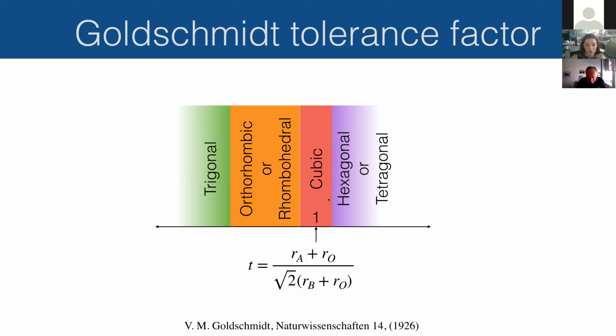If the ratio is greater than 1, you will most likely have a hexagonal or tetragonal structure, and a lot of ferroelectrics fall into this category. If the tolerance factor is now less than 1, you will get orthorhombic or rhombohedral symmetry, like I just showed 2 slides ago. And if you make the tolerance factor even smaller, you'll probably get to trigonal. And if the ratios of the A and B cations are too far away from 1, then you probably will not be able to stabilize the structure at all. It will just simply not exist as a perovskite, whatever material you're trying to calculate.